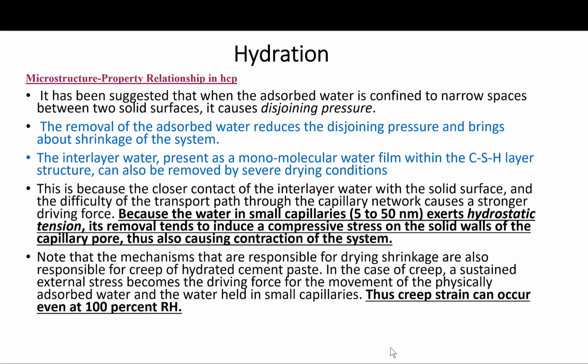It has been suggested that, when confined to narrow spaces between two solid surfaces, the adsorbed water causes disjoining pressure. The removal of the adsorbed water reduces the disjoining pressure and brings about shrinkage of the system.